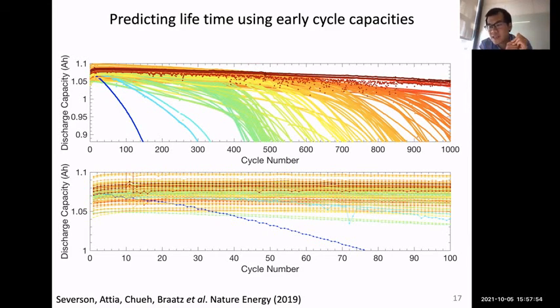The color code represents the lifetime of the battery. Red is very long lifetime. Blue is very short lifetime. You can see that just by glancing with the naked eye, there doesn't seem to be a very strong trend in terms of the initial degradation. In fact, you can see that for the first 100 cycles, the battery capacity really isn't changing. In fact, if I show you the detailed analysis, you can see the capacity is actually increasing rather than decreasing.